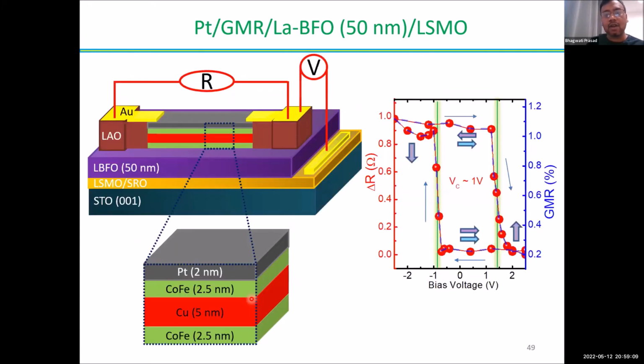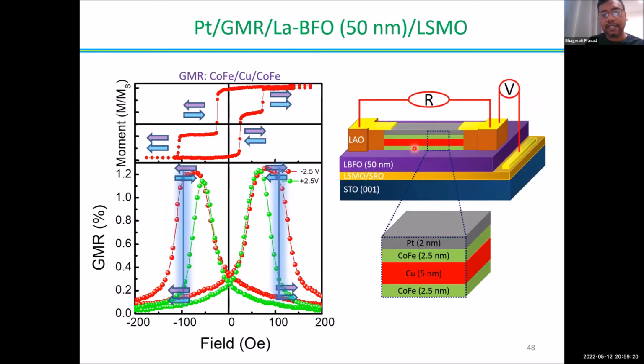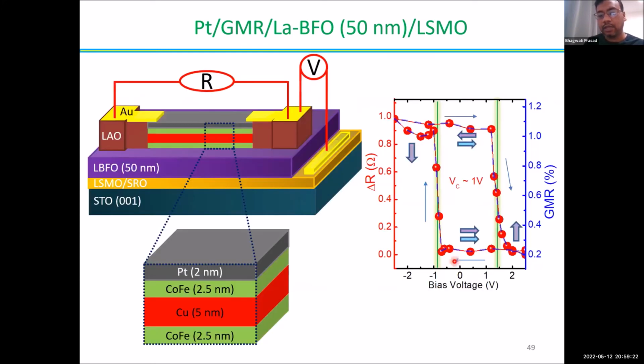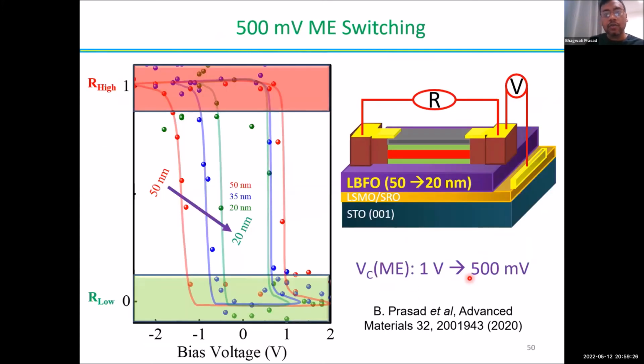And if you have this background field of 100 Oersted, you can switch the device just with the electric field from one state to the other state. So here you basically achieve the same GMR percentage by sweeping the electric field from one direction to the other direction. Okay, so we have systematically reduced the thickness of this LBFO from 50 to 20 nanometer.